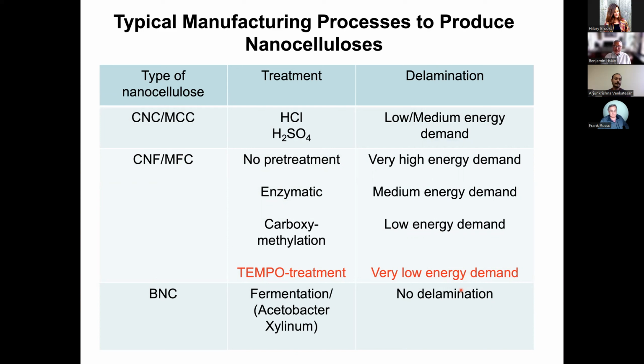And how do you make nanocellulose? Typically, you have two ways to do this. One is the top-down approach. This is called cellulose nanocrystals or cellulose nanofibers. So how does it work? You take a biomass, treated or non-treated, and you use chemistry. Chemistry basically allows you to degrade the lignin part or hemicellulose part. So it's called the pulping process. But the better chemistry also allows you to oxidize the surface of the nanocellulose.